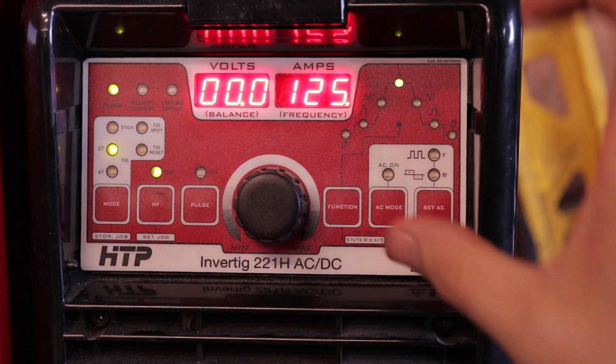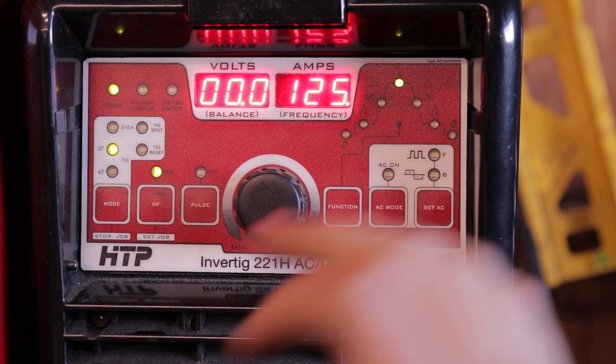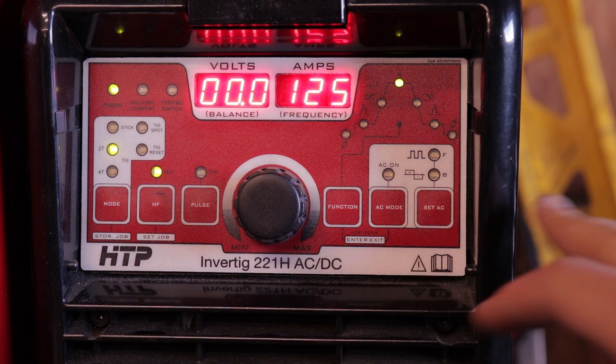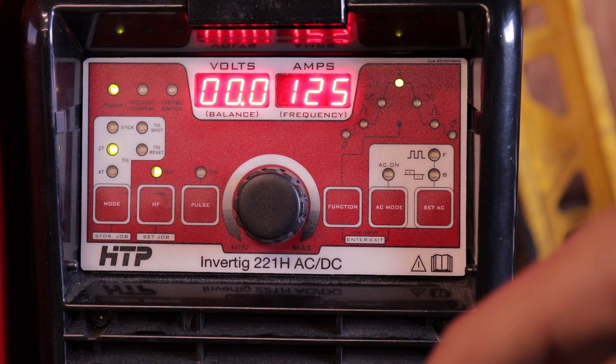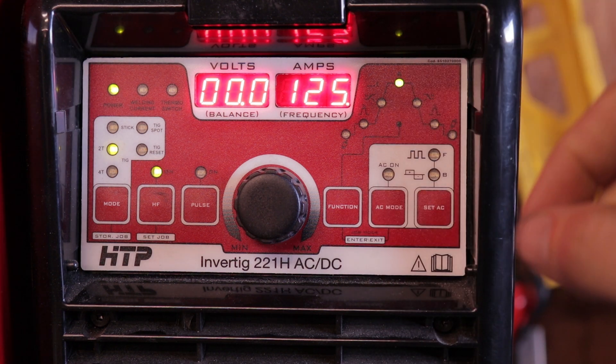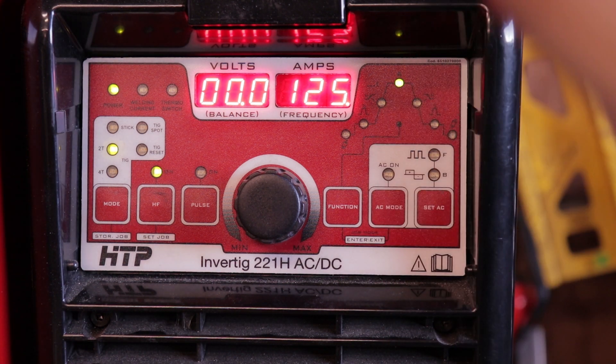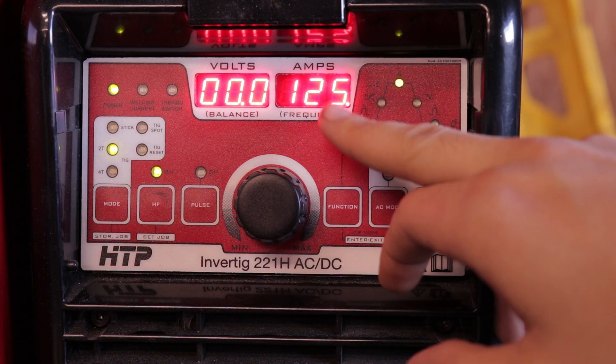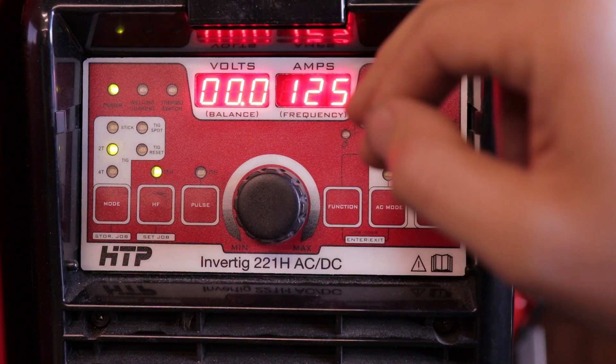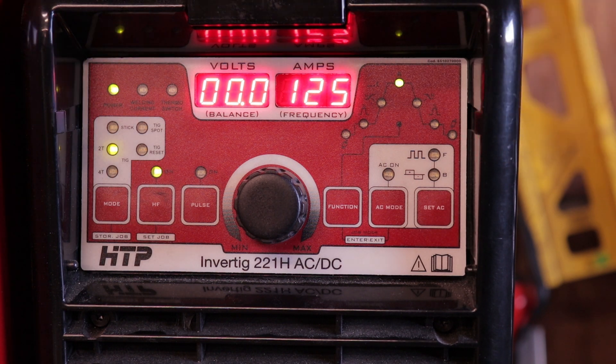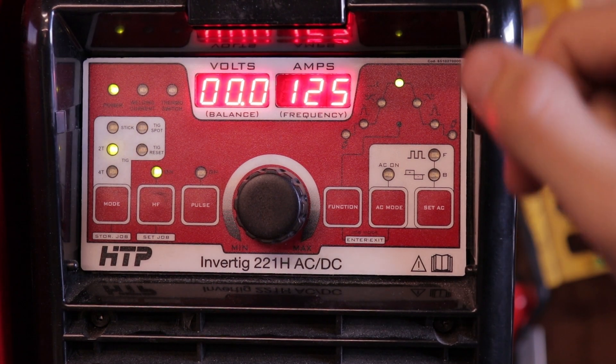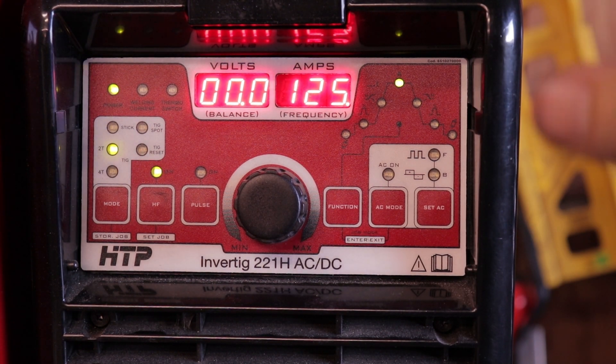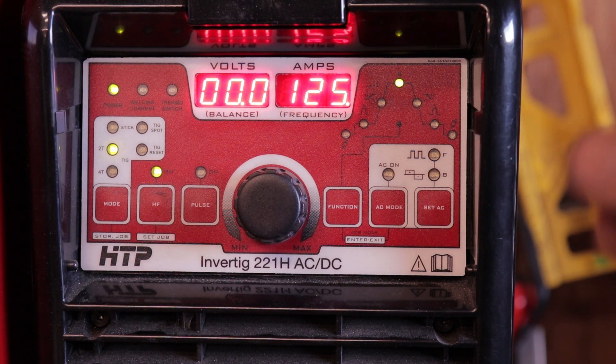So for the stainless outside corner on the eighth inch material, I'm just running high frequency, 125 amps and that's it and I'm just adjusting with the foot pedal. So when I was welding the outside corner, I did one with backing and that was probably pretty close to full pedal of 125 amps. In the shot that you'll see here and then the screen of this, I was probably around 80 amps and there was no backing on it so I was running real quick.